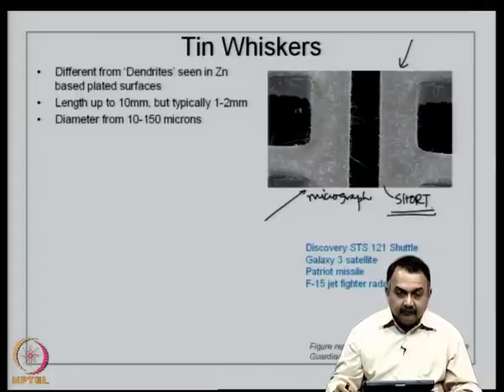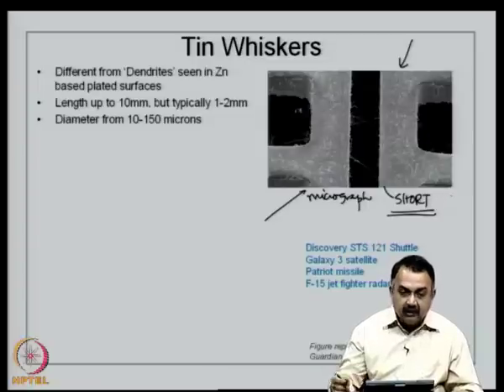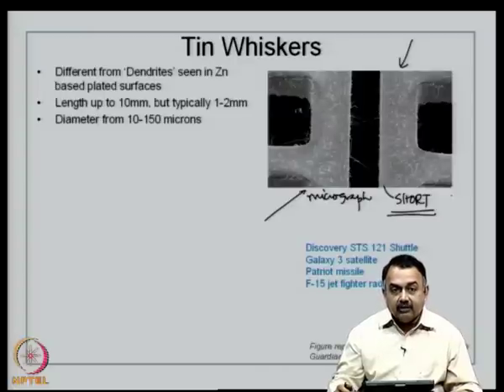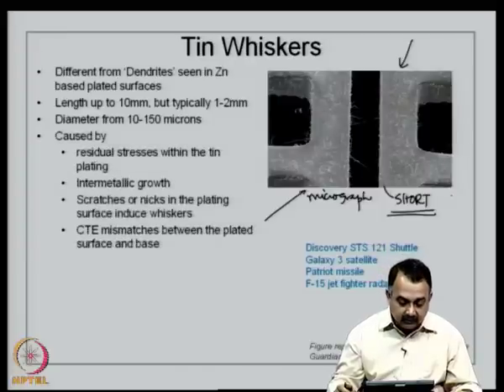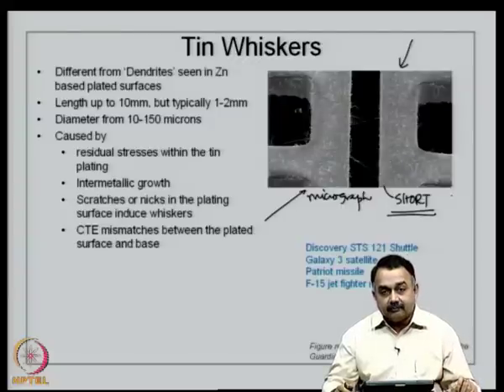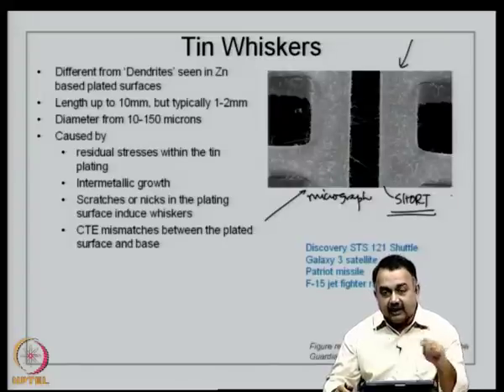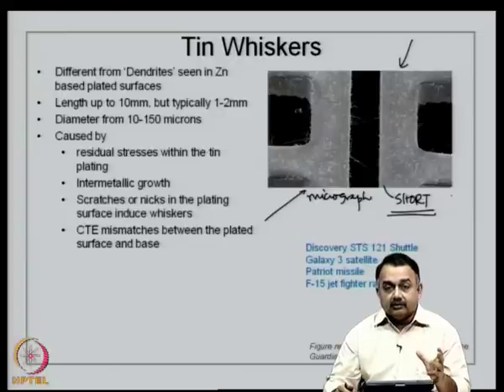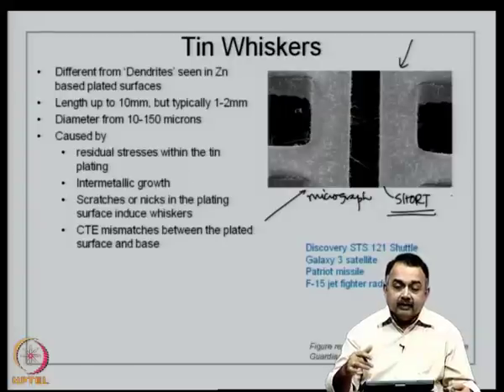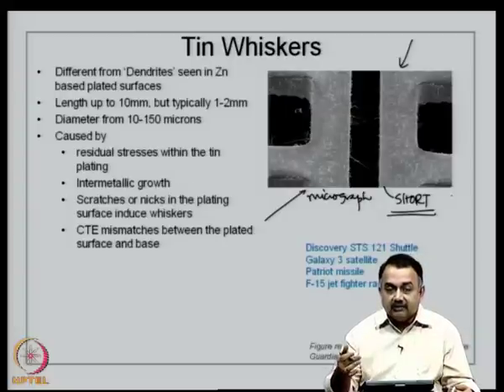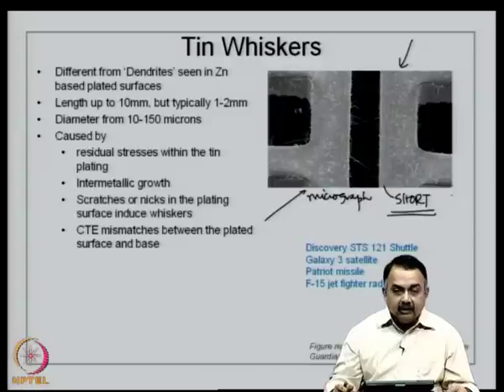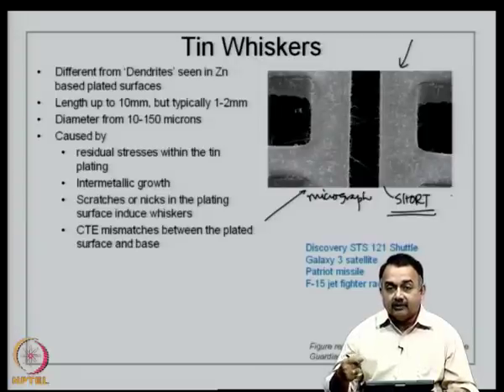and these whiskers are formed due to various factors, which I will explain shortly. The physical parameters of these tin whiskers: typically they can grow up to 10 mm, but typically about 1 to 2 mm very fast, with diameters ranging from 10 to 150 microns. They are caused by residual stresses within the tin plating. So, in a tin plating finish, if you create a nick or a scratch post process, that will be a very good source for tin whiskers to grow, because that is an area where the stresses could be released from the tin thickness that you have plated. Then these whiskers are basically due to the intermetallic growth that your tin exhibits from the copper surface. So, scratches or nicks in the plating surface will induce the whiskers, and could be the starting point for formation of whiskers, and these whiskers grow typically 1 to 2 mm per year.